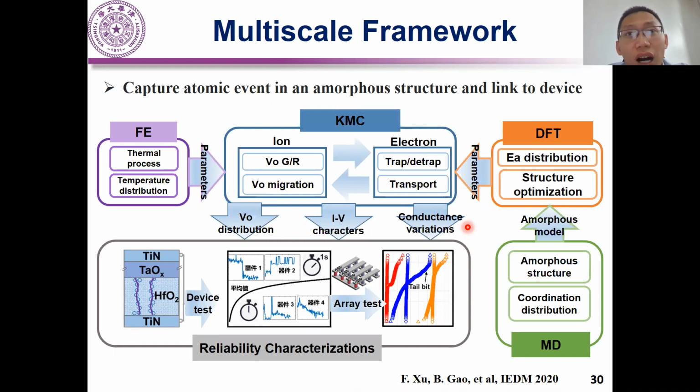So to solve all these issues, we developed a multi-scale framework. The simulation starts from molecular dynamics. We first use the MD method to generate the amorphous hafnium oxide structure, and then use DFT to do the structure optimization.